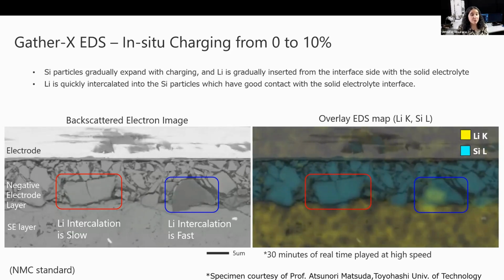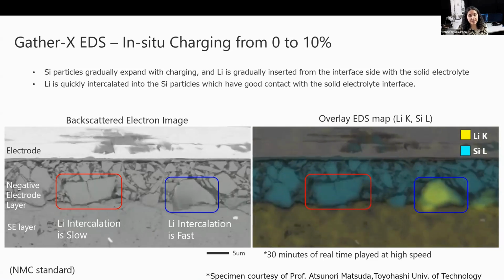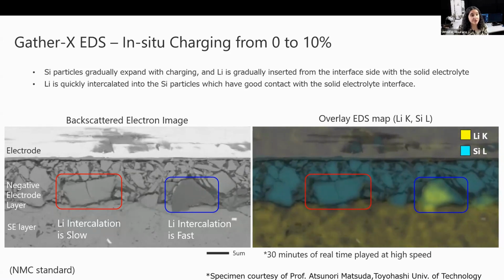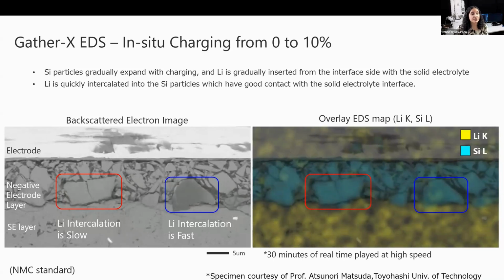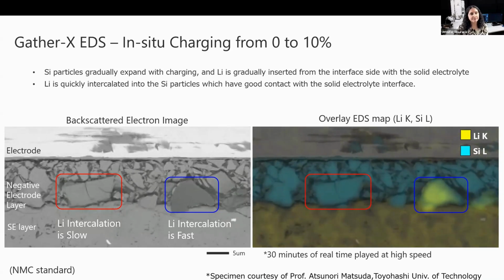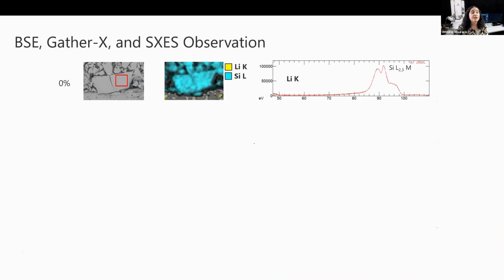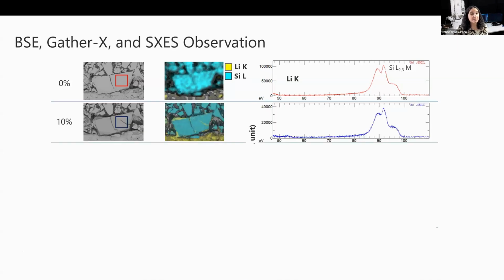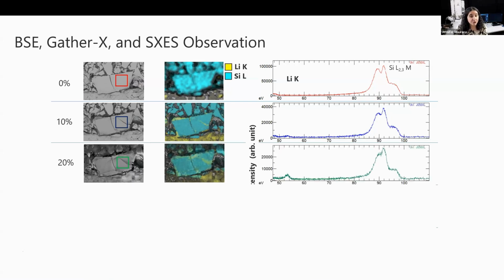Next, we focused on silicon particles with little change in the backscattered electron image contrast in EDS map during the charging from 0 to 10%, and conducted further charging and discharging studies to target them for SXES analysis. So before charging, the silicon L peak is characteristic of crystalline silicon, and we don't see any lithium. At 10%, the peak shape of silicon L changes slightly, and a very small lithium peak is visible. At 20%, the lithium peak intensity increases, and there's a further change in the silicon L peak shape. This is corroborated by the change in contrast in the BSE image and the observation of lithium intercalation from the EDS map.